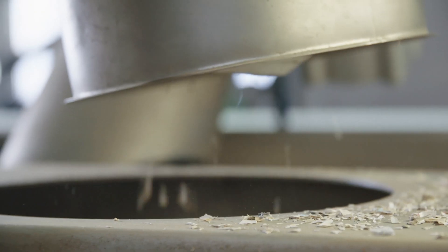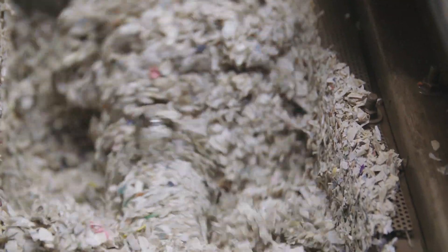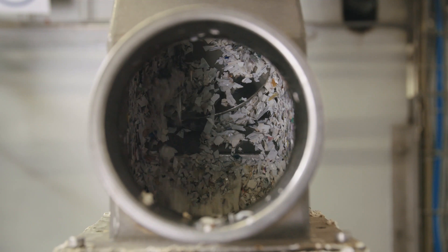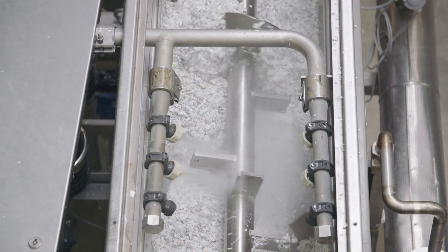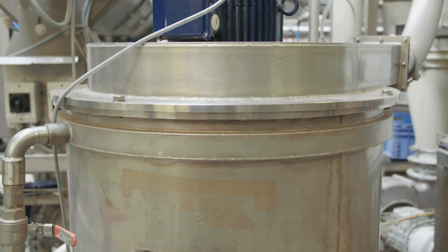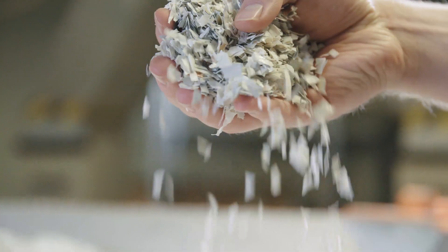These solid fractions, which were formerly polystyrene yogurt cups, are ground into smaller pieces or flakes which are then transported to a hot washing section with a caustic soda solution. During this process, labels and colors on the outside as well as food leftovers on the inside are removed. The flakes are thoroughly rinsed with hot water and then enter into a dryer and an air classifier. After this step, the purity of the polystyrene content is 96 percent.